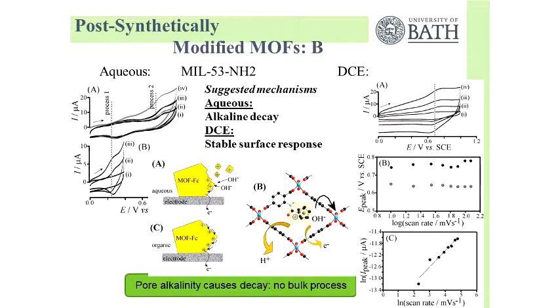If you take the MOF material and put it into sodium hydroxide, that's a normal process for analysis of zeolite materials. This actually is going to dissolve the inside out. So it's not good for our plan to absorb CO2 and reduce it, but it's very interesting to look at these pore processes.